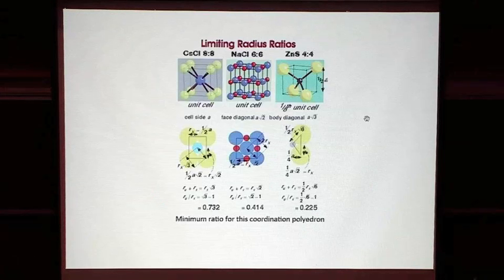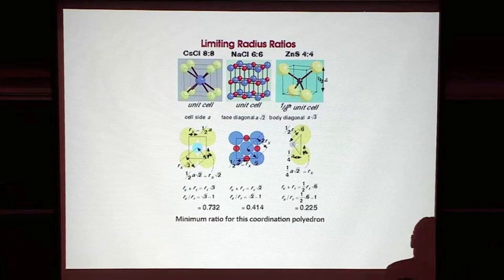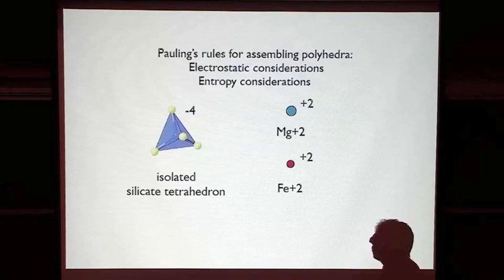If it's above a certain number here, 0.73, we have 8-fold coordination, then 6-fold coordination, then 4-fold coordination, and so on. And of course, for silicon and oxygen, that falls very strongly within, at least at low pressure, the tetrahedral coordination, and so we end up with tetrahedra. This isn't actually drawn in, but magnesium and iron tend to be, they're not always, but they tend to be in octahedral coordination at low pressure.